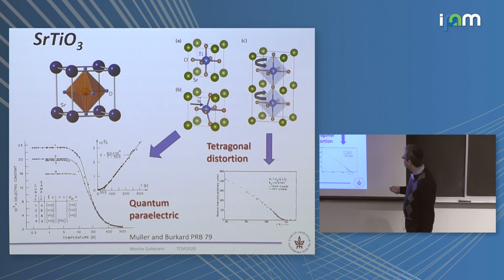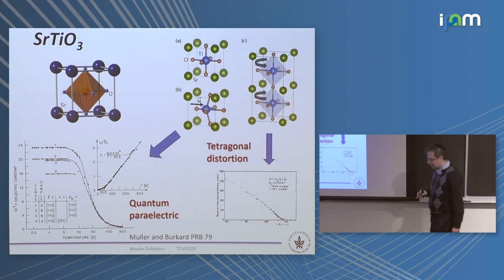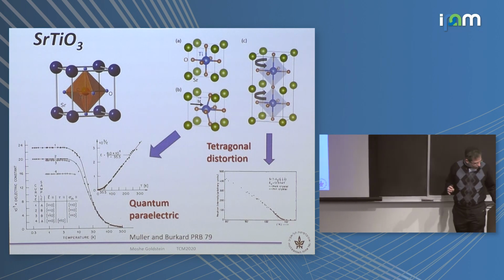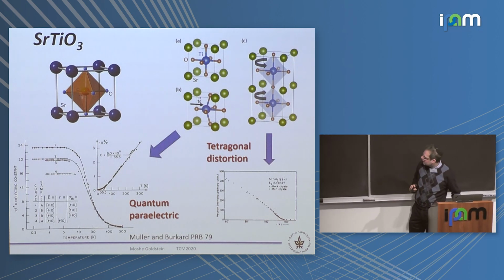Another thing that happens to this material is this. As you lower the temperature below 105, there is a slight tetragonal distortion. The octahedra in adjacent cells rotate, and from cubic, the symmetry is actually reduced to tetragonal. This is not going to be so important in what's going to go on, but still it's good to keep in mind.